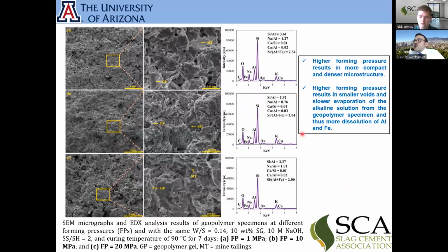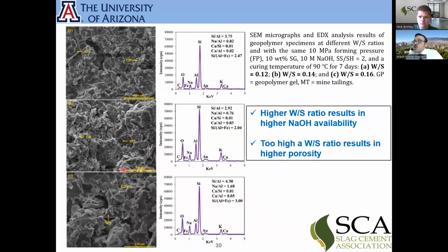If you want to check the microstructure, this tree shows the forming pressure effects. So first with the 1 megapascal forming pressure, then 10 megapascal, and then 20 megapascal. And we are seeing that by increasing the forming pressure, the microstructure is denser and the UCS is higher. What about the water to solid ratio? At a constant forming pressure, if we are increasing the water to solid ratio, the porosity is increasing and the UCS is decreasing. But as we discussed in the graph that we showed, a good combination of the forming pressure and water to solid ratio will provide you a better cementitious material.